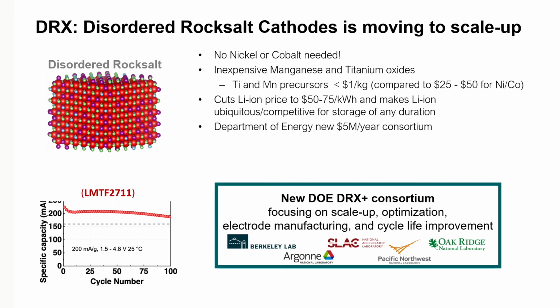This is now a large program of the Department of Energy. The Department of Energy just set up what's called the DRX Plus consortium, which is a $5 million a year consortium for 3 years to solve the remaining problems to scale up these materials and bring them to industry. And if this works, the outcome will be important, right? Because we can work with titanium and manganese precursors instead of nickel and cobalt. These cost about $1 a kilogram compared to about $25 to $50 for nickel and cobalt. So this could bring lithium ion down to something like $50 to $75 a kilowatt hour, at which point it is really hard to beat for any other technology. So we'll see if we get there.